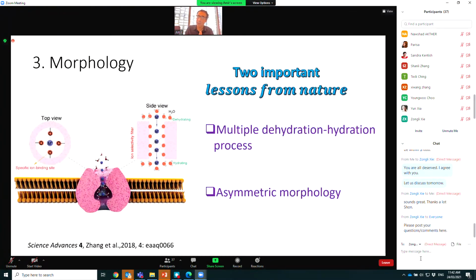And the third parameter is morphology. If I'm going to tell you something based on all of our research over the last 5 years on creating membranes for lithium extraction, it is that morphology plays a very critical role here. It's very important, and it matters how we play with morphology. Nature actually does that. If you study the biological ion channels, you see they are designed in a very good way over millions of years of evolution. So they have very good selectivity, high selectivity, and also high permeability.